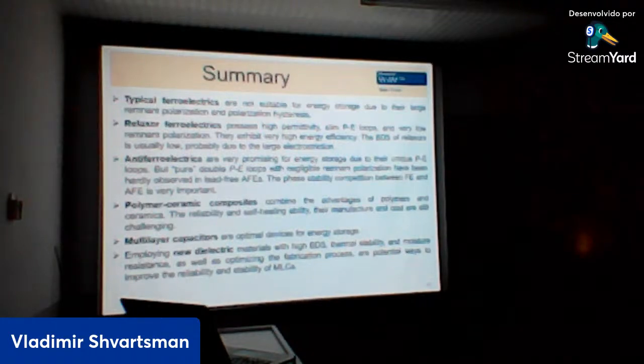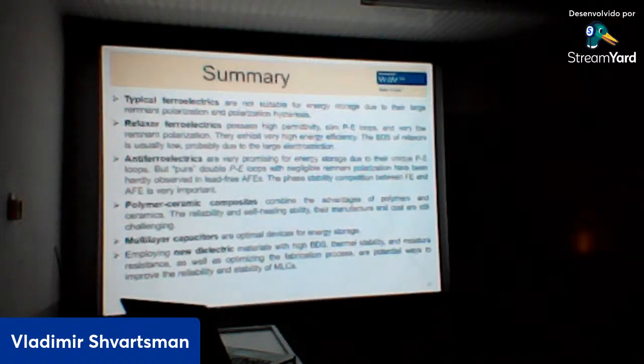Okay, I would like to summarize my presentation. Typical ferroelectrics are not suitable for energy storage due to their large remanent polarization and polarization hysteresis. The relaxor ferroelectrics have a high dielectric permittivity, slim polarization loops, and very low remanent polarization. They exhibit very high energy efficiency, but their breakdown strength is usually low due to large dielectric permittivity and large electrostriction. Antiferroelectrics are very promising for energy storage due to their double hysteresis loops, but pure double loops with negligible remanent polarization have not often been observed. And important is the phase competition between ferroelectric and antiferroelectric state in these materials.